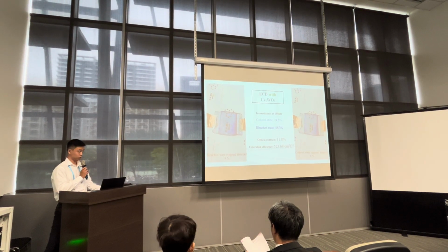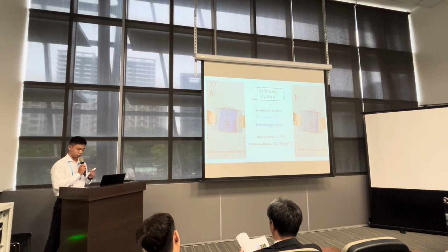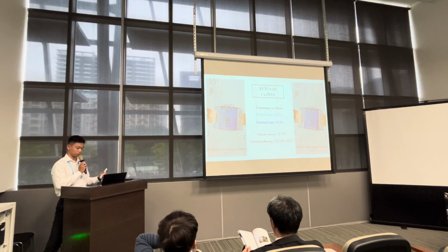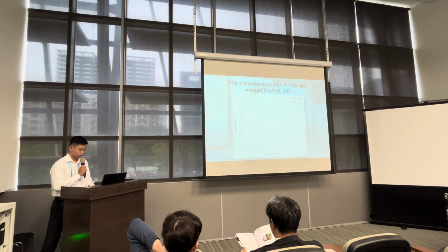And the next is during the fabrication process, the nanoparticles will show the phenomenon of agglomeration. This agglomeration has little effect on the transparency, but it actually creates more contact area between the electrode layer and the electrochromic layer. So you can make the reaction more vigorous and more efficient.